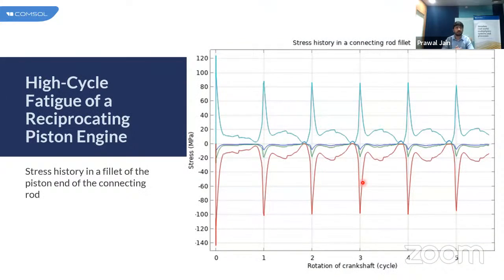The graph that you see is the stress history in a fillet of the piston end of the connecting rod. One may have a question: why are we seeing a stress history just on the fillet? A fillet is chosen since the stress concentration due to geometrical change is expected there, and a few revolutions must be computed before a steady state behavior is obtained. Here we can see that from cycle three, the stress history for each consecutive cycle seems to repeat itself. Both the peak stress and the stress cycle are about the same almost after the third cycle.